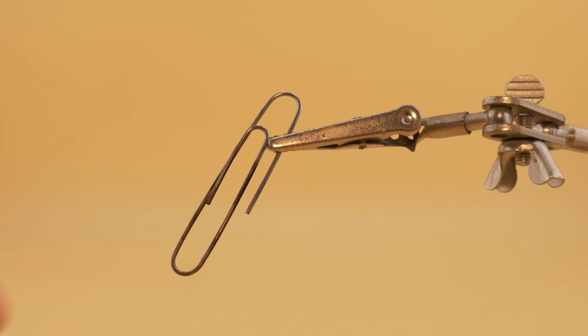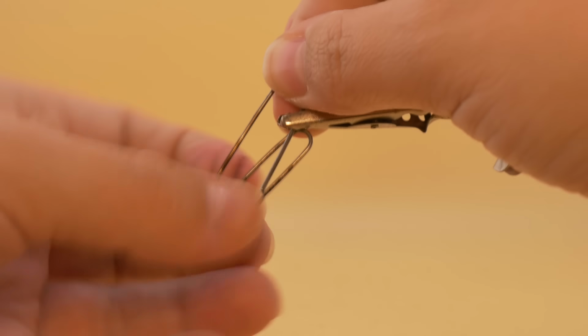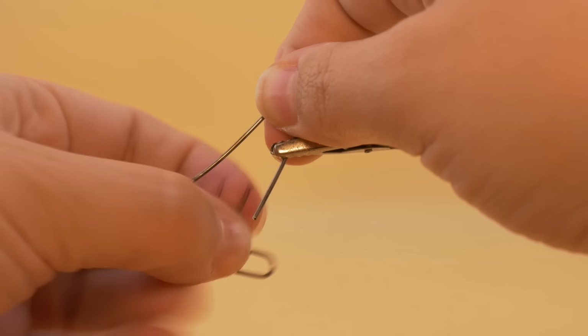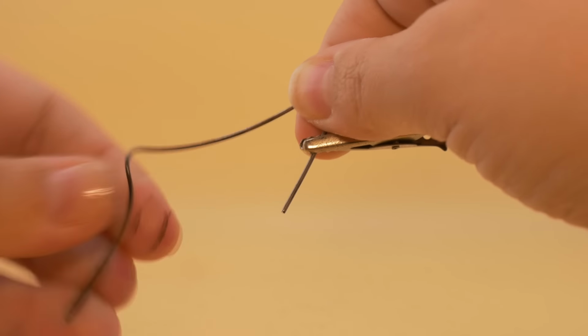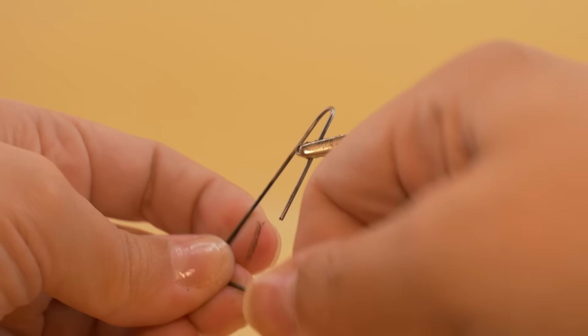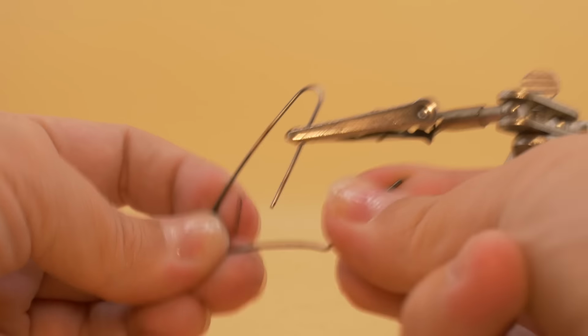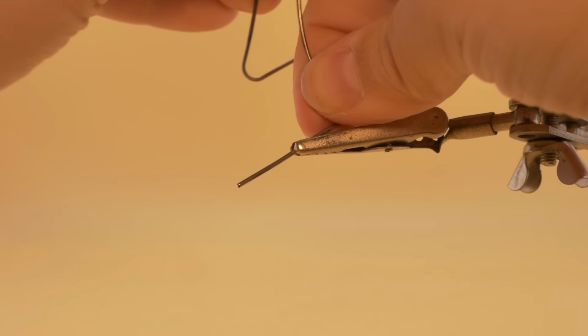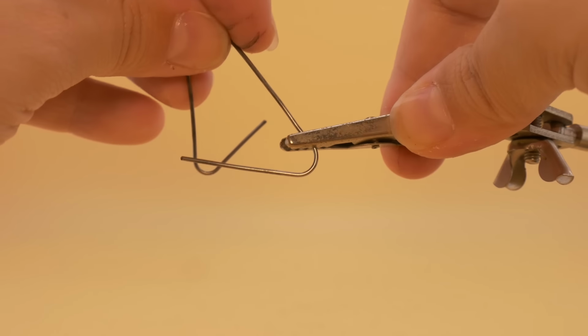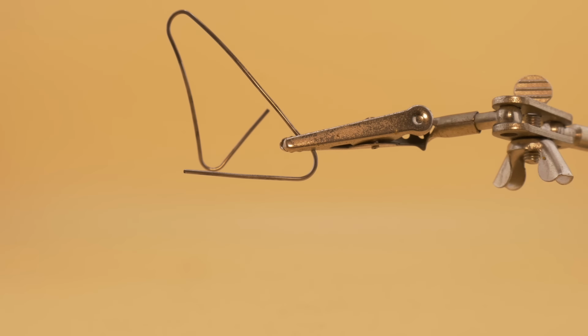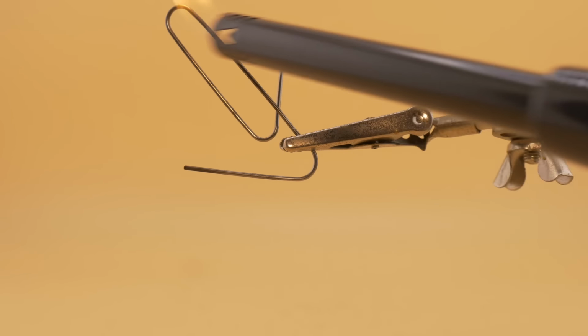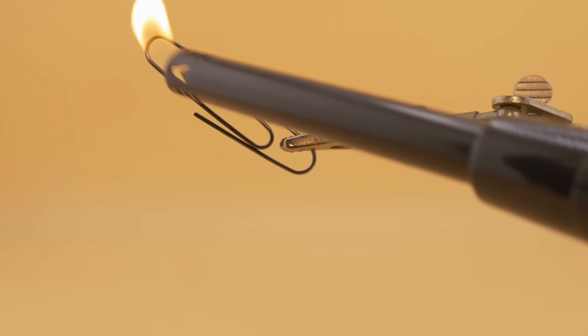Now, what I have here is another famous titanium intermetallic, or alloy. It's nickel titanium, commonly known as Nitinol. This is roughly an equal mixture of nickel and titanium, about 50-50 atomic percent. Nitinol doesn't form a simple mixture, it forms an ordered phase that gives it remarkable properties, shape memory, and superelasticity. Now, this almost seems like magic.